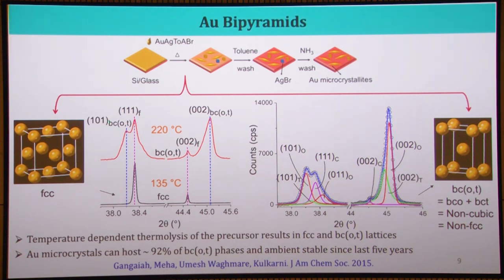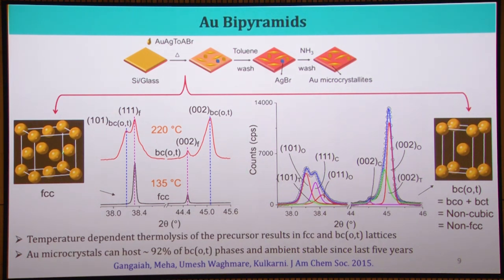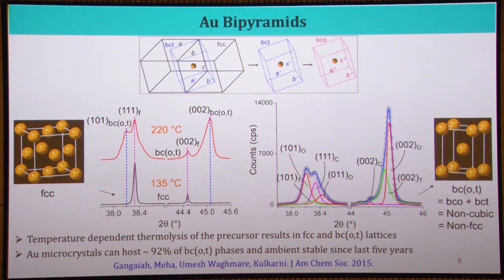After several months of struggle to fix the space group — doing profile fitting — we identified these as signatures of body-centered orthorhombic (BCO) and tetragonal (BCT) phases hidden in the diffractogram. XRD works up to the fourth decimal in angstroms, so that's the assuring factor, and the chi-square values guide you in fixing the crystallography. What happens structurally is: a perfect FCC is distorted into tetragonal or orthorhombic depending on slight changes in the a, b, c parameters. By virtue of symmetry you also bring in one atom at the center, making it body-centered. If you take two FCC unit cells you can make one BCT — this is the BCT expression of the FCC, but when you cause a variation in the c/a ratio it becomes fully tetragonal, and that's what happened in our case.